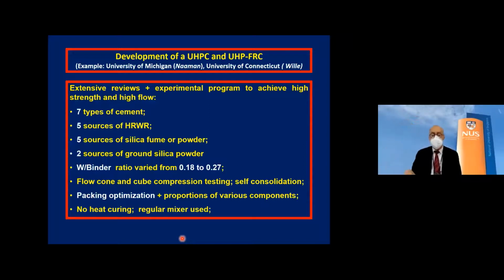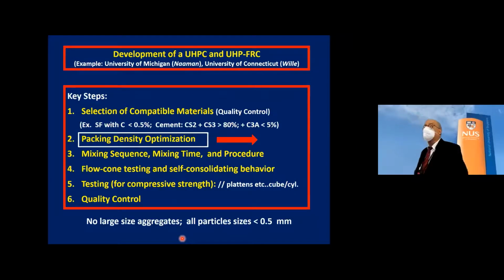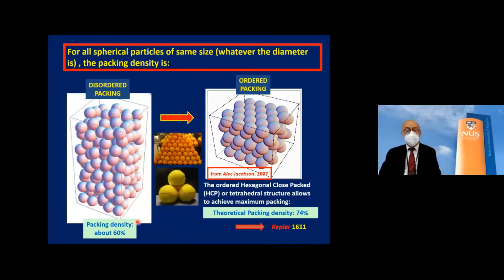But I want to mention something that we don't think about, and that's the packing density optimization. And if you haven't done it before, this is visual and you might like it. If you put spheres of equal diameter in a container, their packing density turns out to be about 60%. That is, the volume of the sphere inside the volume of the container is 60%. However, if you organize these or you put them in this pyramidal form, it's called ordered hexagonal close pack structure, like this, then you get 74%.